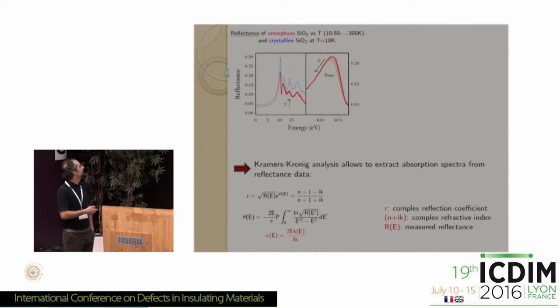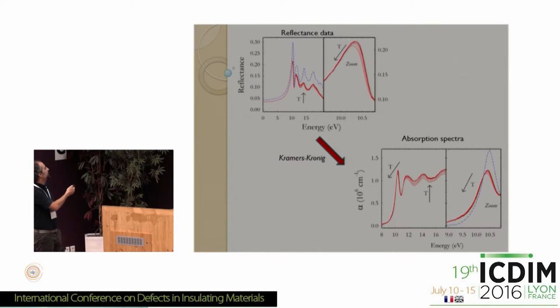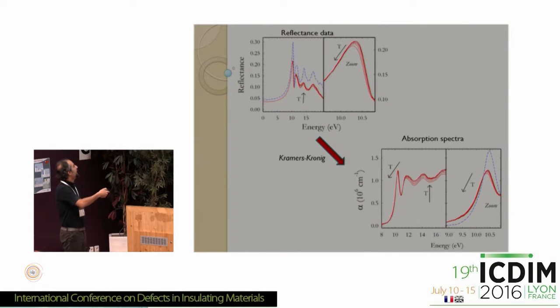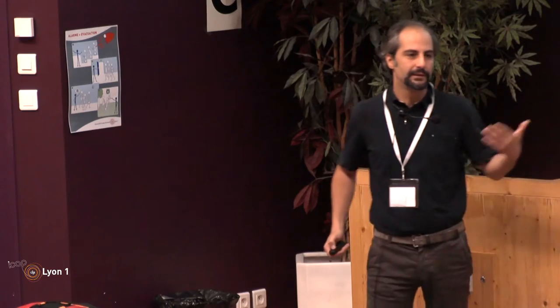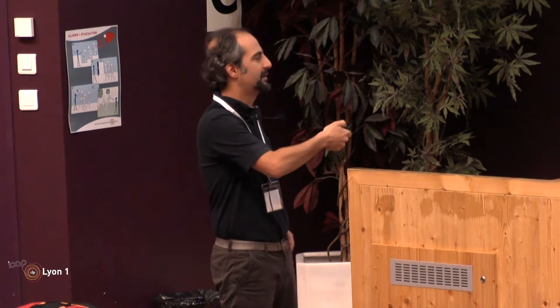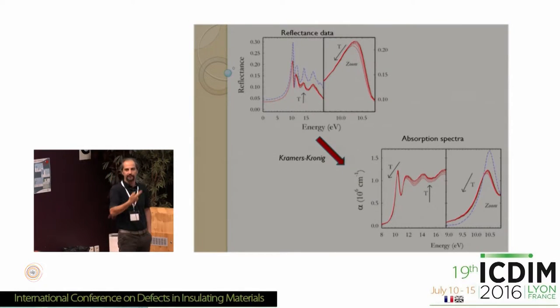Now, the nice thing about reflectance is that it can be connected to absorption by what people know as the Kramers-Kronig relationship. The Kramers-Kronig relationships are mathematical relationships between the reflectance and the absorption, basically, or if you want, between the real and imaginary part of the refractive index. So from the reflectance measurements, provided that you have data on a sufficiently wide range, it is possible to calculate the absorption coefficient as a function of energy, which is exactly the same thing that you would theoretically obtain by measuring directly the absorption coefficient. Except you can't, because here the absorption coefficient of the sample is about 10 to the 6 centimeters to the minus 1. So this is not something you can really measure directly.